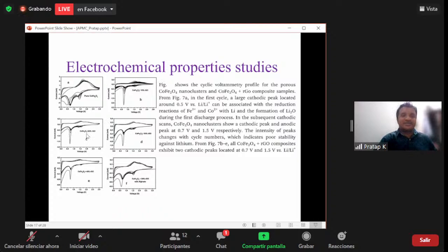So look at this cobalt ferrite with 20%. In the previous case, we found that this is the good sample. Since this is the good sample, in order to avoid the capacity fading, whatever we planned earlier is adding some binder into it. So this sample is added with sodium alginate binder, and it is brought into the CV again. When it is brought into the CV again, you can see that it is occupying a large area. When it is occupying a large area, it means that it has very good capacity.